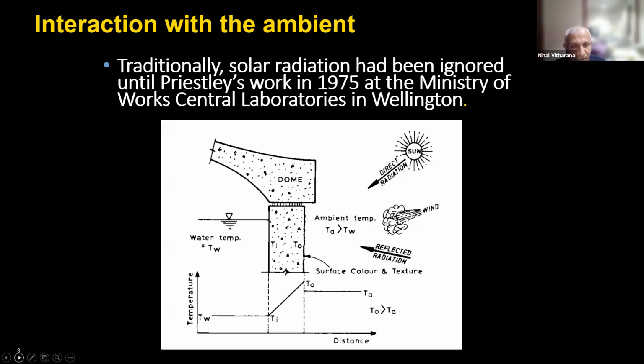This is just to get into the real problem. What you see is a concrete tank. It could be a concrete tank or a sludge sewerage digester, where solar radiation is incident on the external surface, while the internal face retains the temperature of the water or sludge. As it is a big thermal mass, it remains constant. So this sets up a very transient, peaky thermal gradient. If the wall is thinner, as you can see, the temperature distribution would be almost linear. But if it is thicker, it will be highly nonlinear. I will discuss both things during this webinar.